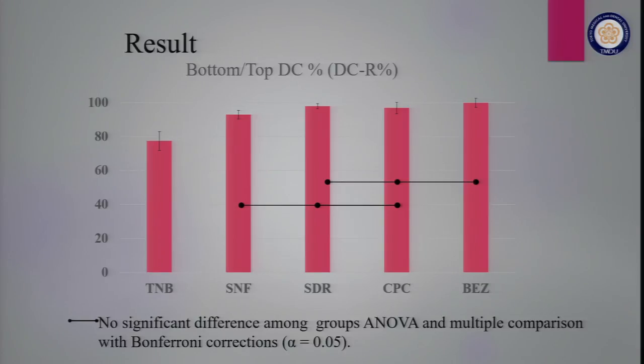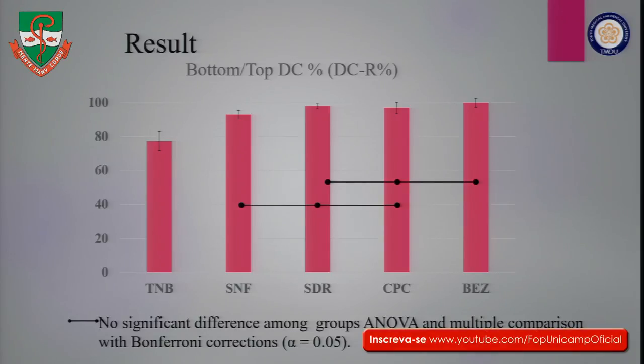And when we evaluate the degree of conversion at the bottom of the cavity, this material showed the least conversion. It means less polymerization, less shrinkage stress. Okay, we need much better polymerization in this kind of material. That's why, unfortunately, at the moment, most of the so-called bulk fill composites cannot work as we expected.